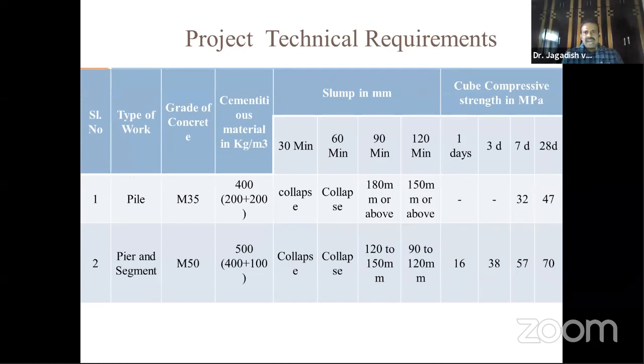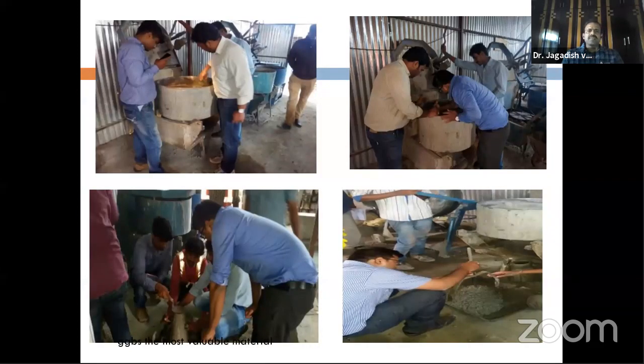You can see the slump at different delayed timings, and you can also see the 28-day strength achieved. For M35, they got 47, and for M50, they got 70 MPa. So these are some of the trials, the initial trials before giving the mix to the client. One of my friends, Mr. Yogananda, with whom we have conducted a combined project, is from JSW. He was present in this slide.